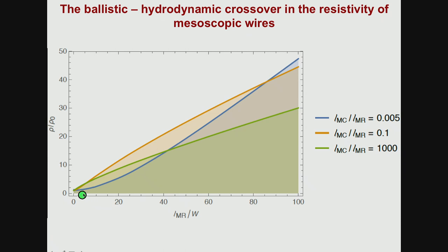Here you have kinetic calculations giving you 3 different predictions. The color scheme is pretty horrible, but just look at the lines. If you have LMC 1,000 times LMR, then you're just in the ballistic regime, right? Because for a given wire size. Whereas if you have LMC 5,000ths of LMR, you'll be in the hydrodynamic regime. And the difference is that the hydrodynamic regime shows this curved onset and quite a low resistivity at low values of this ordinate, which is a dimensionless one that I think I shouldn't spend ages explaining.